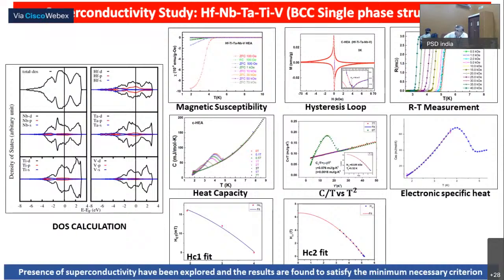Now the same material was taken for a superconductivity study. Why have we taken it? As I was telling you, in high entropy alloy the Fermi surface is broken into Fermi bands, and you can see how these are occupied. When we did the DOS calculation, the density of states calculation, it shows there is a region where it can have a very high tendency for superconductivity. And these are the curves shown experimentally. You can see that as the temperature is brought down below 4K, it started showing superconductivity at various temperatures.